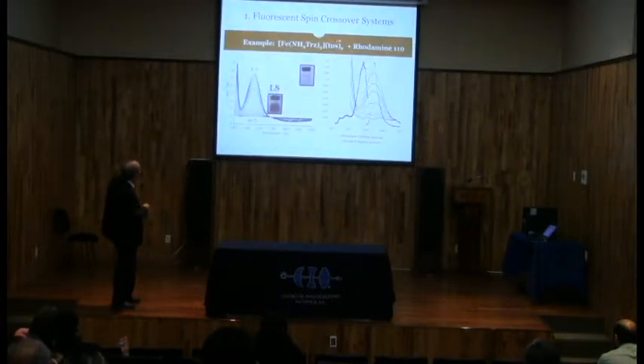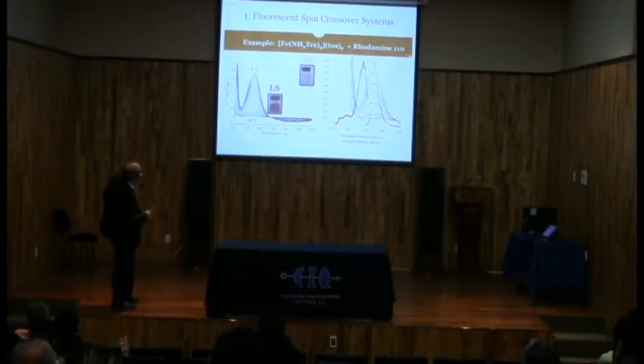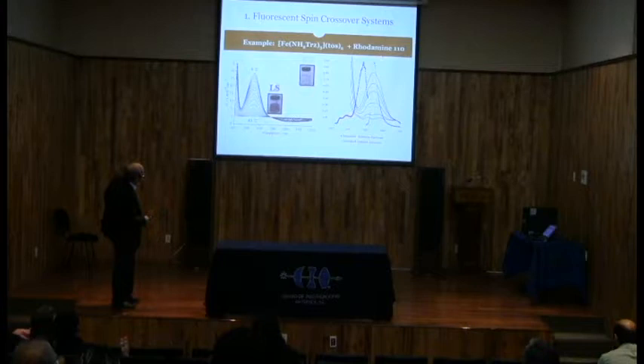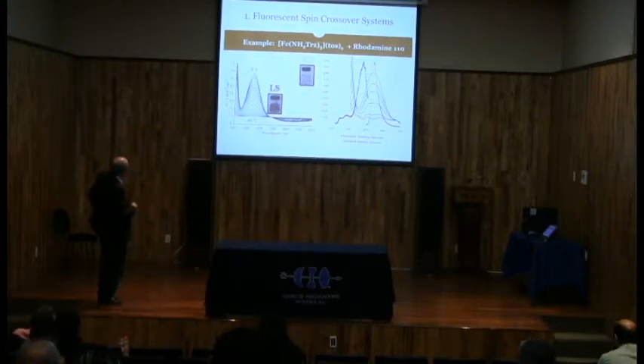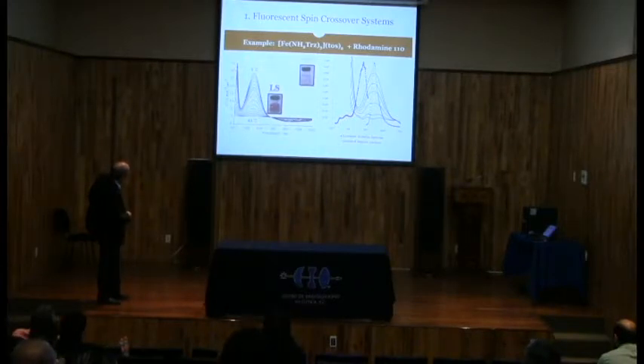We wanted to combine the spin crossover system and luminescent rhodamine complex here. Why rhodamine? Because rhodamine, as you know, is emitting in the green region. If you look at the optical properties of the spin crossover, you see that the low spin state absorbs in the green region here. But the high spin form is transparent, there is no absorption.